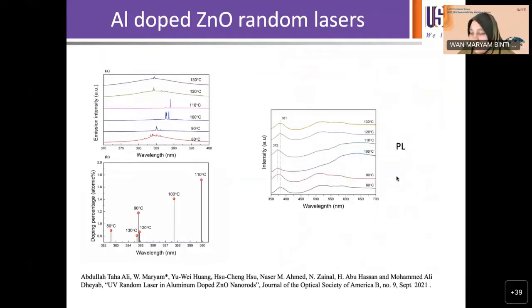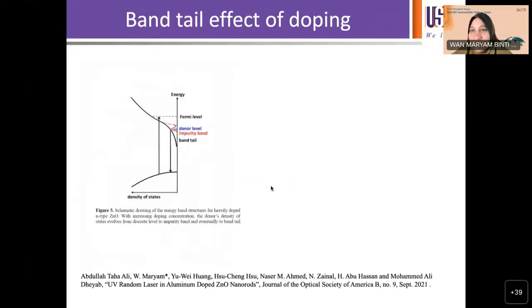Okay, and what we notice is that there is a red shift in our lasing, right? What we did is a single shot lasing spectrum, as you see here in A. So we saw this red shift at around 1 milliwatt pump power. And this is very similar to the photoluminescence spectrum that we observed. So there is something called the band tail effect that is occurring in our sample due to doping.